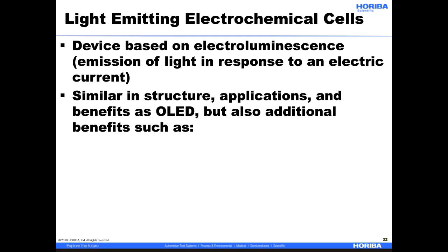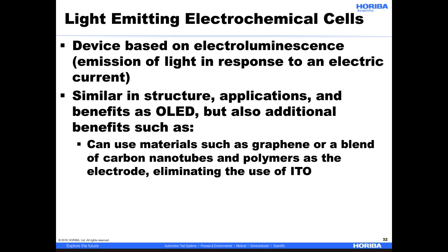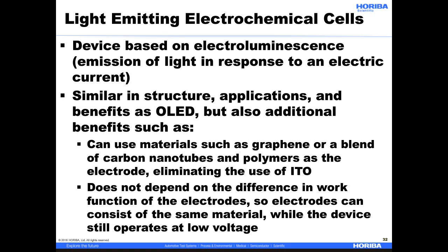They're similar in structure, applications, and benefits as OLEDs, but there are also additional benefits. These include that you can use materials such as graphene or a blend of carbon nanotubes and polymers as the electrode, and thus eliminate the use of indium tin oxide. It also does not depend on the difference in work function of the electrodes, so the electrodes can consist of the same material, say gold, while the device still operates at a low voltage.